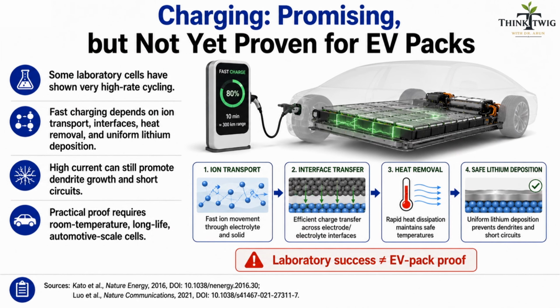Now, the most exciting claim: the 3-minute charging. In 2016, Kato and colleagues reported a sulfide electrolyte with a very high ionic conductivity. Ionic conductivity means one thing: how easily lithium ions can move through the material. Their laboratory cell operated at an 18C rate, which is roughly a 3-minute charge or discharge rate. Impressive. But look closely, the especially low resistance was demonstrated at 100 degrees Celsius. That is not a normal EV charging condition.